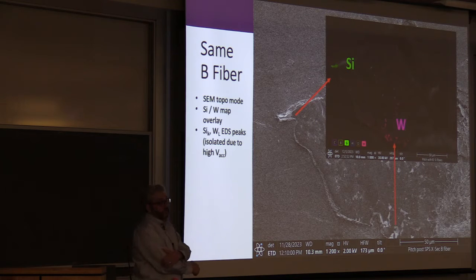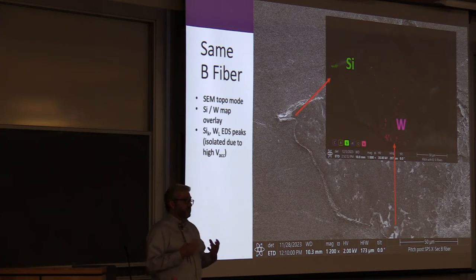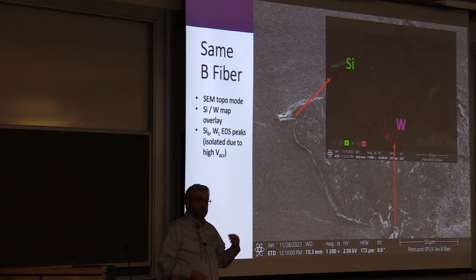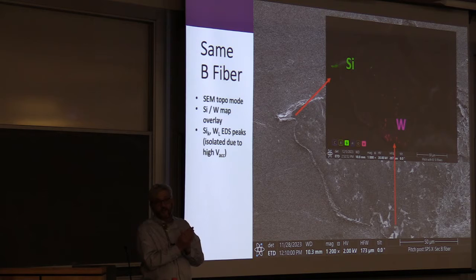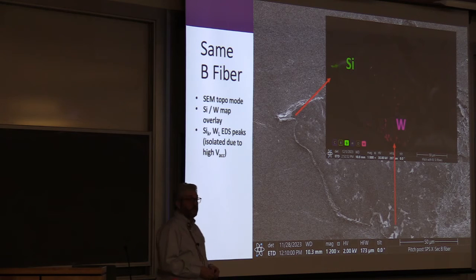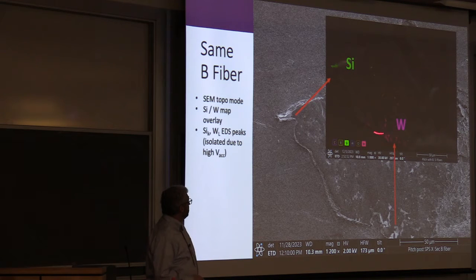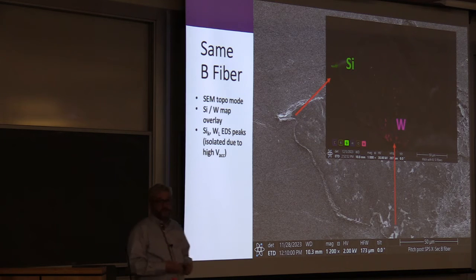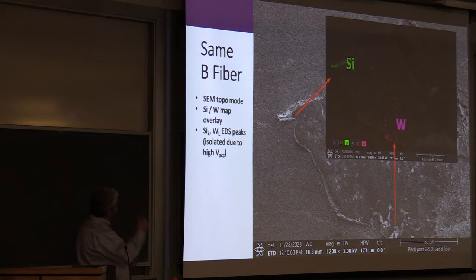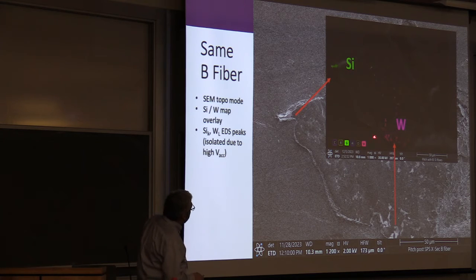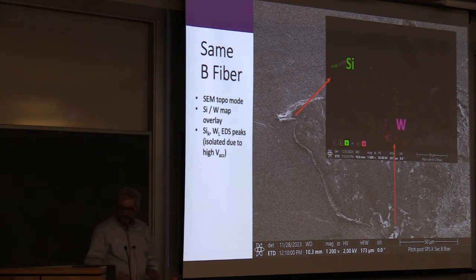accelerating voltage on the EDS, you can separate the silicon and the tungsten, which at low kV you have a nice overlap, and unless you do deconvolution, it's really hard to separate the two. But at high kV, you get distinct peaks, and you can separate the two. So, now, I was seeing silicon, and there's this boron, and it's actually boron carbide now. It's been converted, and I got tungsten all over the place.